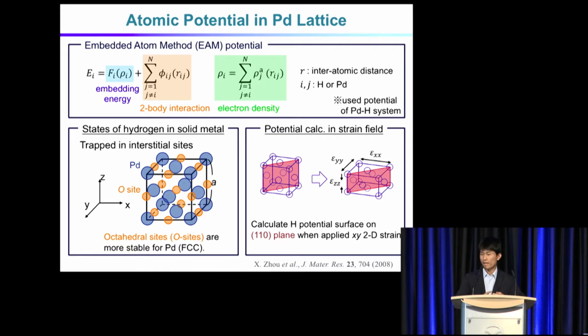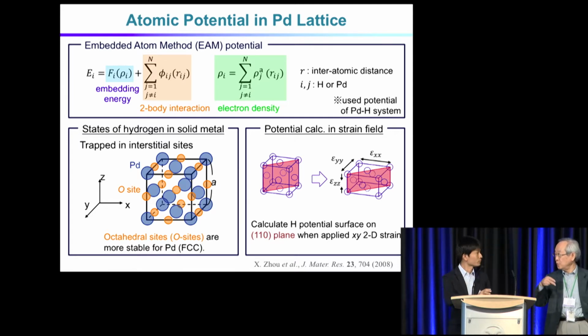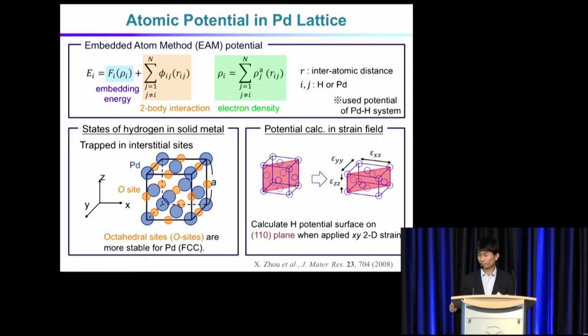We used an EAM potential method to calculate the two-dimensional potential surface inside our palladium plate. But unfortunately, we didn't have data or parameters for deuterium. So we used the case study of hydrogen inside palladium.